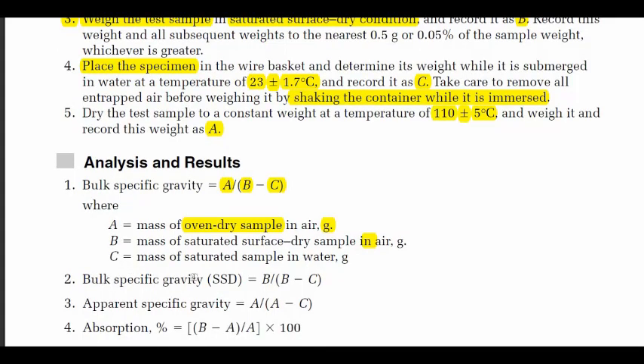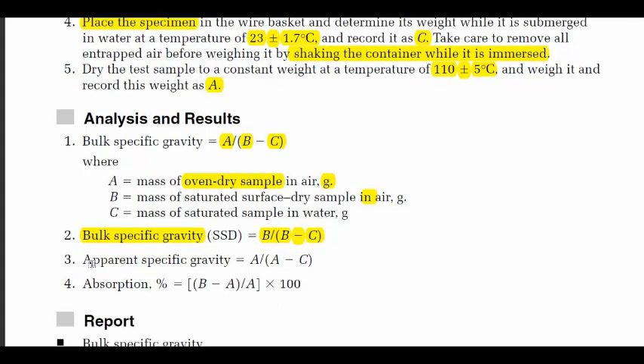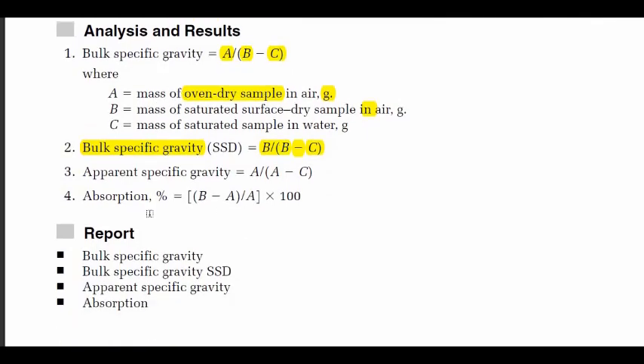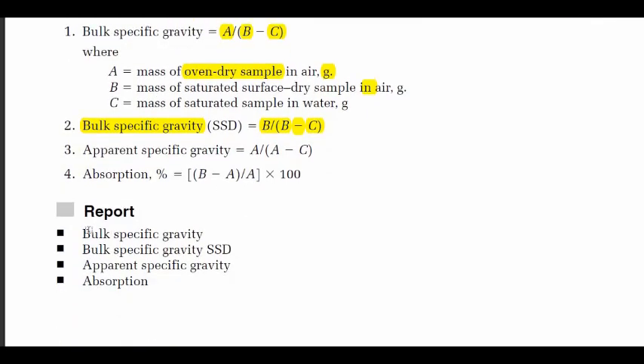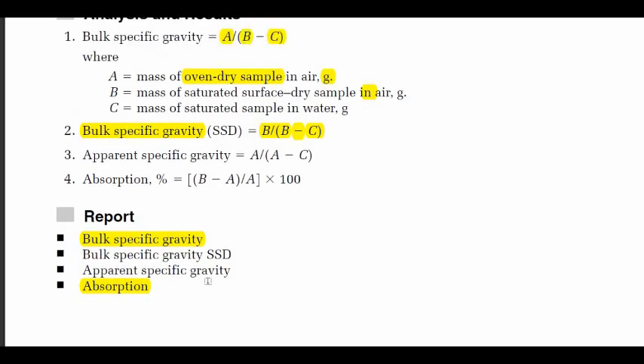Then the bulk specific gravity SSD, saturated surface dry, is going to be B over B minus C, and apparent specific gravity is A over A minus C, and absorption in percent is going to be B minus A over A. Then after having this, we are going to report. So we are going to report the bulk specific gravity, bulk specific gravity SSD, apparent specific gravity, and absorption. This is in summary what we are going to do in our experiment. Thank you.